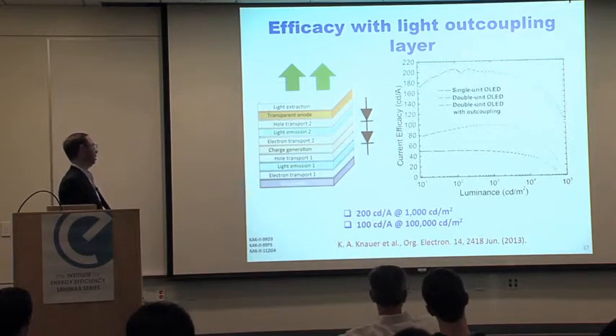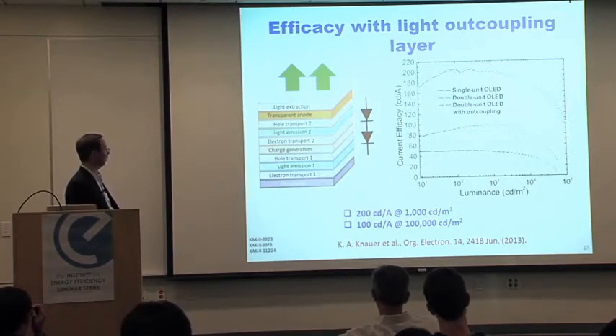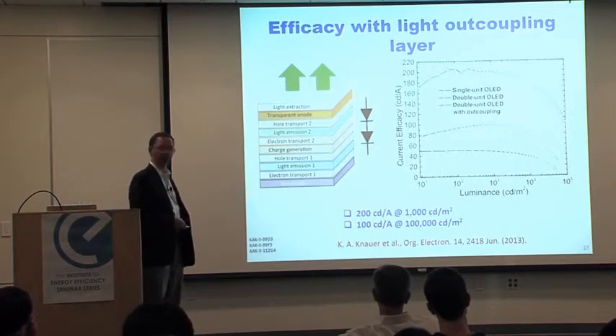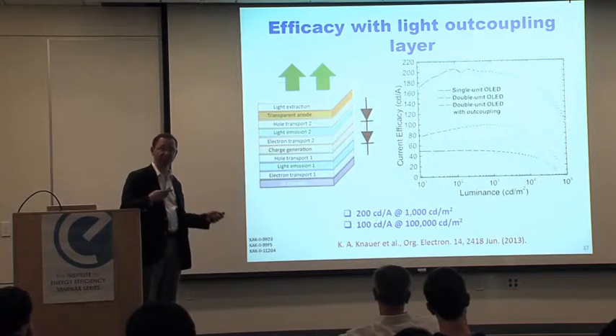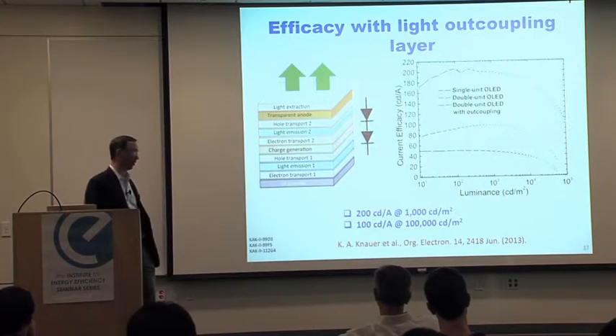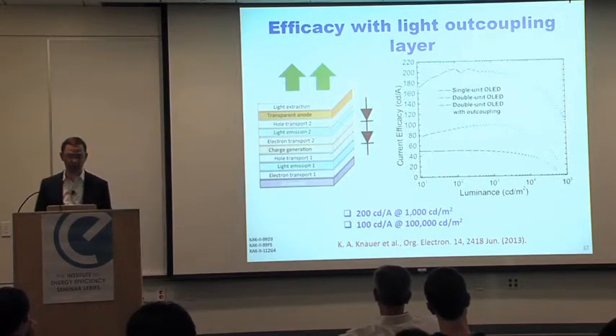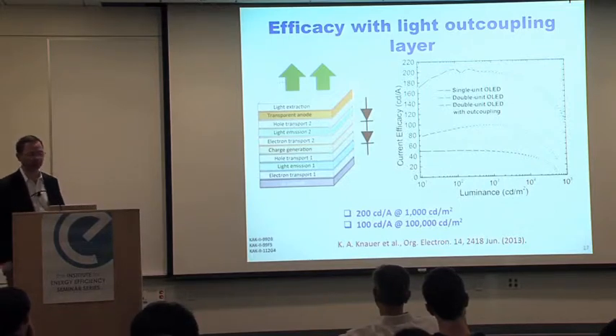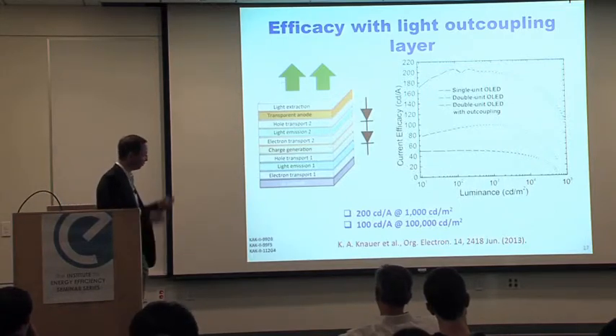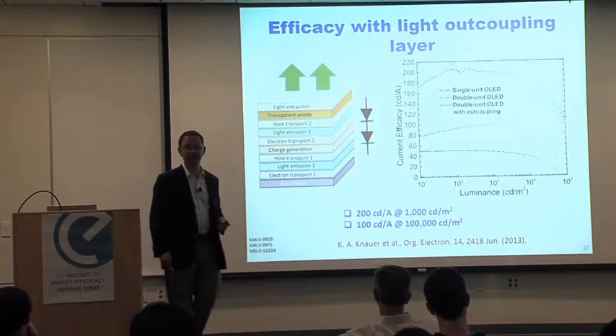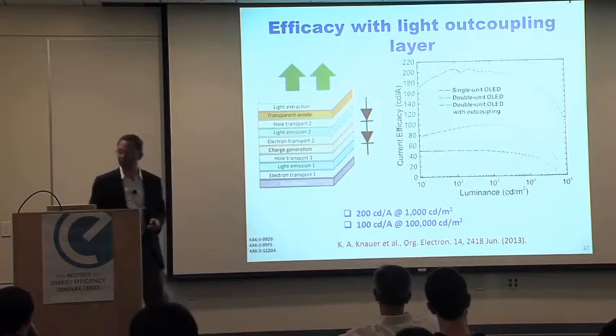And so you can see that now with these multi-junction devices at 1,000 candelas per square meter, we can get 200 candelas per amp. And at 100,000 candelas per square meter, which is a really bright device, you can still get about 100 candelas per amp. So a lot of light, and you have to start worrying about protecting your eyes when you deal with light sources like this.